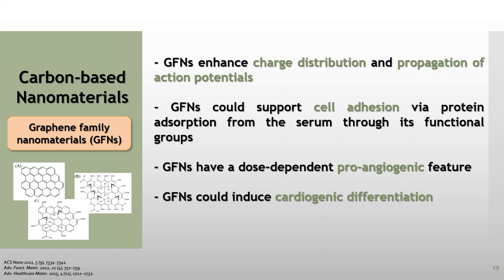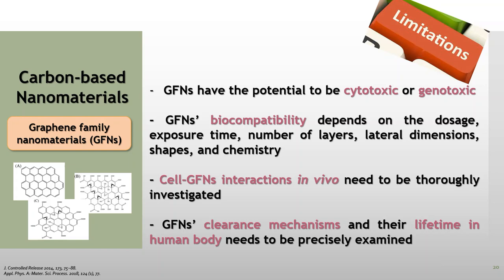GFNs could also induce cardiogenic differentiation. Although numerous studies confirm the promising characteristics of GFNs for cardiac tissue engineering, researchers should address challenges for cytotoxicity, genotoxicity, and biocompatibility. Biocompatibility of GFNs depends on the dosage, exposure time, number of layers, chemistry, as well as shapes and lateral dimensions of these materials. More importantly, cell-GFN interaction needs to be thoroughly investigated in vivo. The mechanism of clearance of GFNs and their lifetime in the human body needs to be precisely examined, which can provide a platform for safe clinical application.